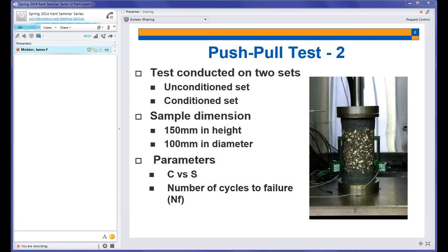This is the setup of the push-pull test. As you can see, this is the complex modulus sample, similar dimension. We glue it to a bottom and a top cap, and then we screw those caps to the fixture. And then, as you can imagine, we apply tension, compression load until failure, and those are the extensometers that measure the deformations.